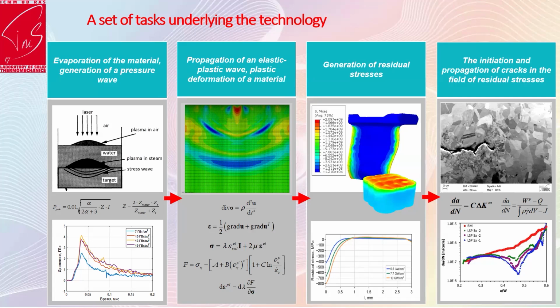We defined 4 steps to apply this technology to industry. First step, we have to investigate the physics of plasma and calculate the stress, strain rate, and the dependence on the impulse. Second, we have to calculate plastic deformation, very specific plasticity, and up to now we use quite a simple approach which is included in standard software. After, we have to calculate the residual stress. We have to simulate the process with a complex shape. And finally, we have to investigate the effect on fatigue. We have solved all steps, not fully solved, but we have a solution for each step, and we can move from the beginning to the end and focus on the result.